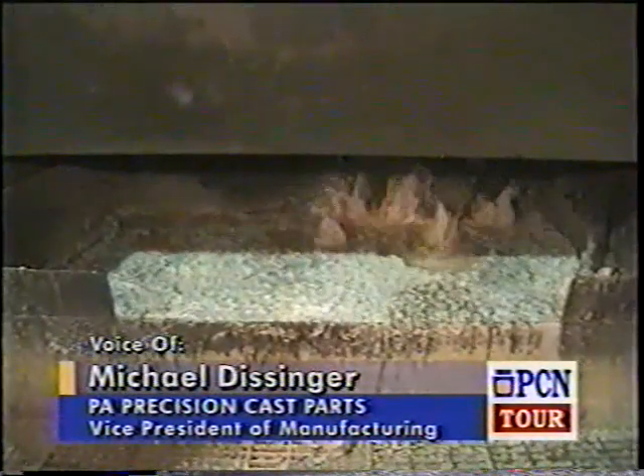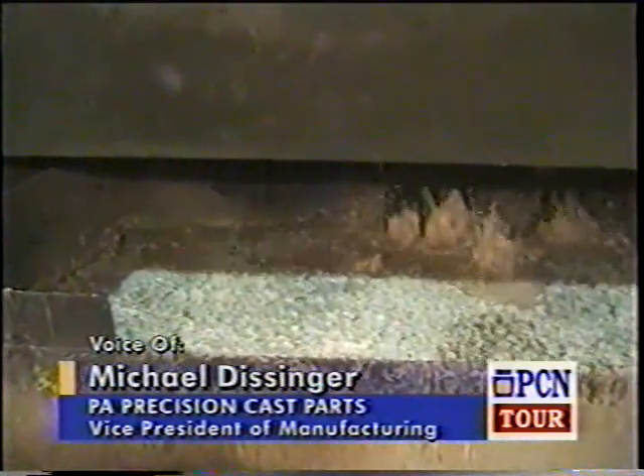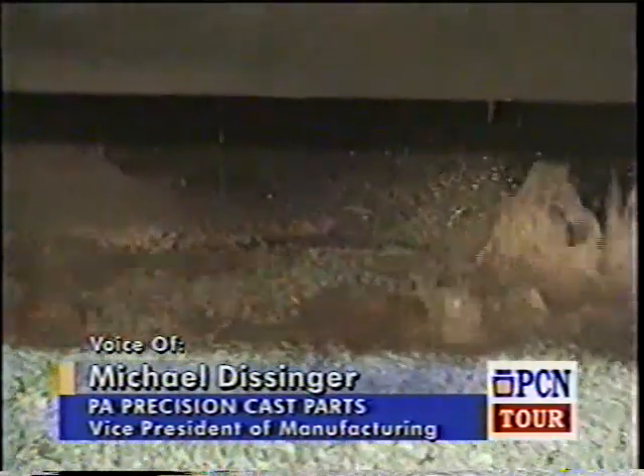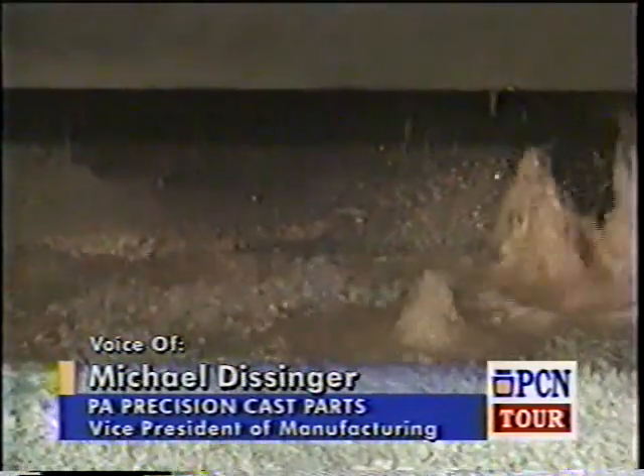We're behind the flash fire dewax oven now, and you can see the wax coming out of the hearth. Again, there's 8 molds inside. It takes about 15 minutes for these molds from start to completion. The wax falls into a water trough, which we have aerated, which just causes a gentle turbulence, which keeps the wax from catching on fire.